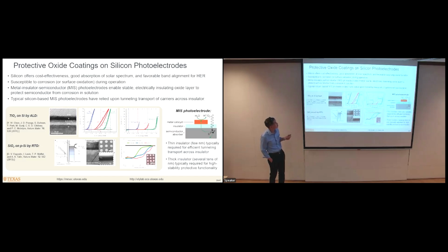So one approach to addressing this problem is to create what are called metal insulator semiconductor photoelectrode structures. So you have a semiconductor absorber over here, say silicon. Then you put some protective layer on its surface. All right, and typically this will be an electrical insulator. Okay, that protects it from the aqueous solution. Then you put a metal catalyst on top that accelerates the reaction, and then there you have it. So that can address the stability issue, but you've traded the problem of stability for the problem of getting the mobile carriers, the photon-generated carriers, across this electrically insulating layer, right?